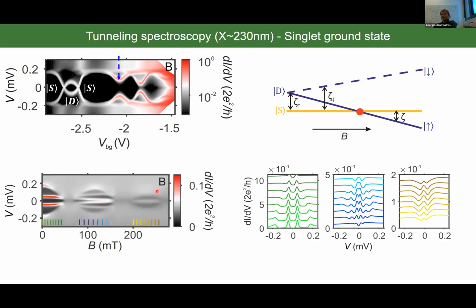Indeed, if you now fix your gate voltage at the blue position and you measure differential conductance versus bias and magnetic field, you can see the evolution of the Andreev bound states, and we end up with a zero bias peak in the second lobe, and that can be beautifully seen in the line scan. If you take line scans in the first lobe, you start with 4 peaks. The middle ones approach and merge to create a zero bias peak, while the outer ones move away. And throughout the second lobe, you have a zero bias peak.